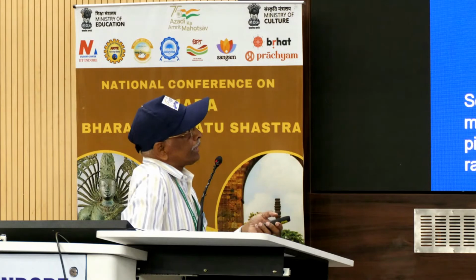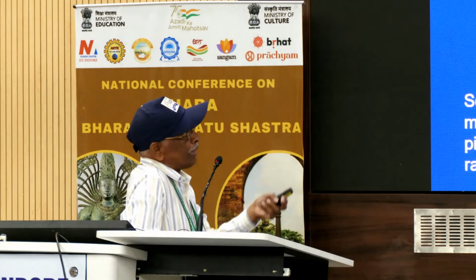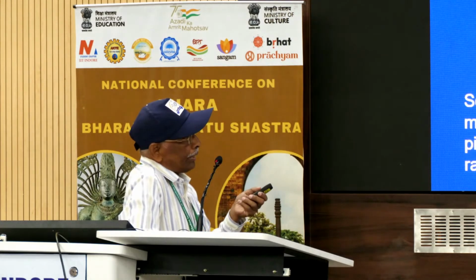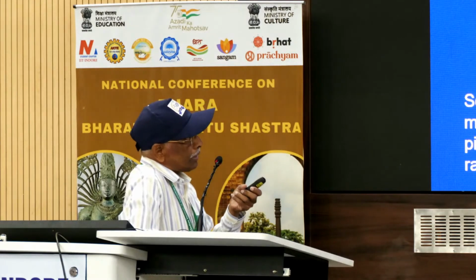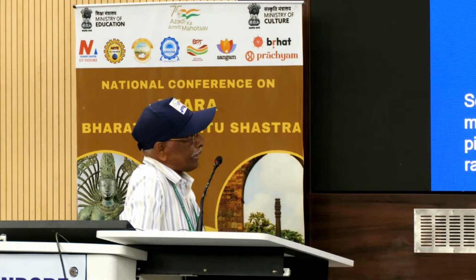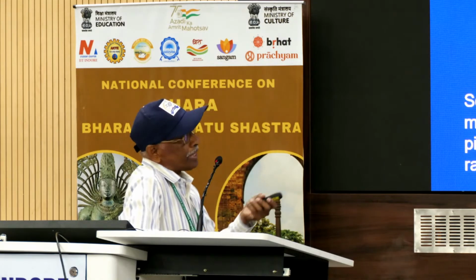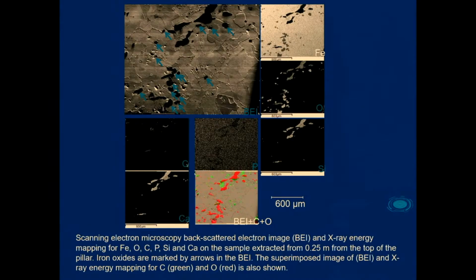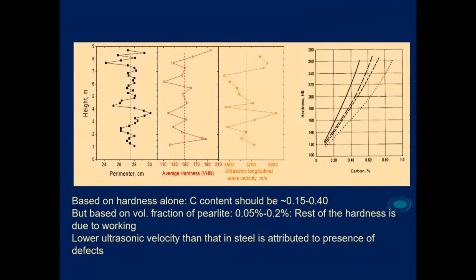So then we did the investigations, we did various elemental analyses and all, and you can see that there are some carbides, that is the cementite, and also we have calcium based slag inclusions. So this is again a ferrite pearlite structure with slag and also the carbide precipitates, what you can see here.